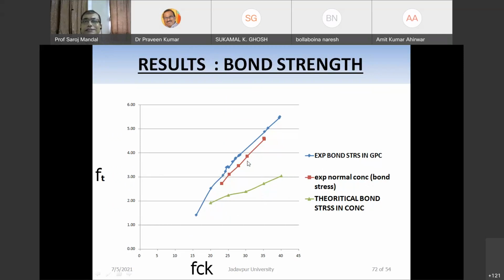So now you can see that our bond value in case of geopolymer concrete is higher compared to the normal theoretical bond stress normally used in our concrete design, and even it is higher than the experimental value. So we can safely say that all the formulations we use for normal concrete can be used for geopolymer concrete.